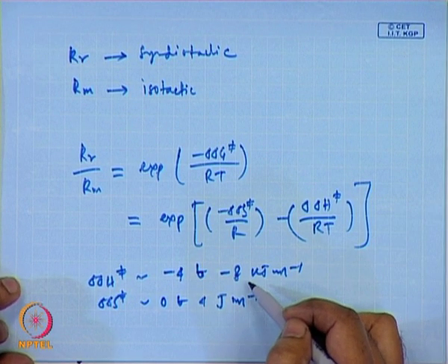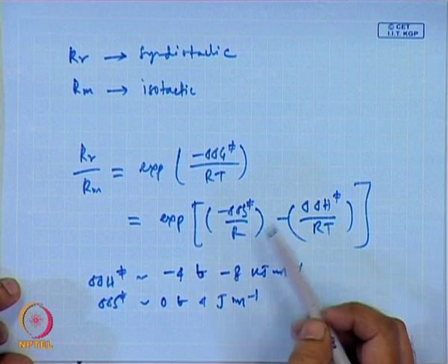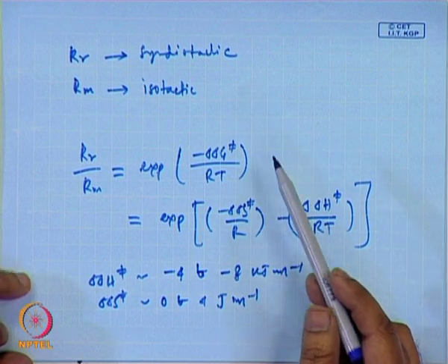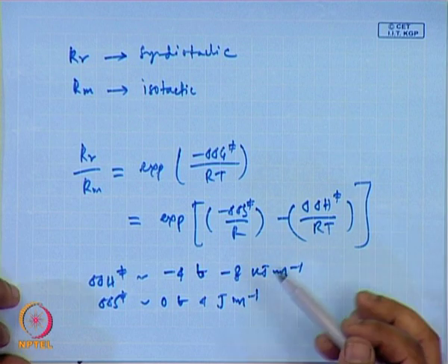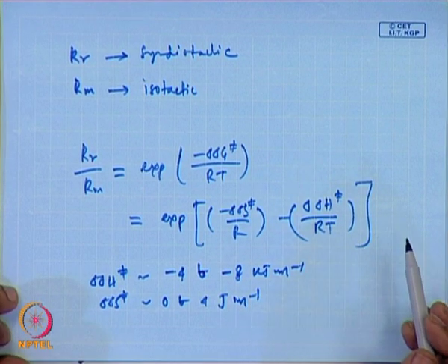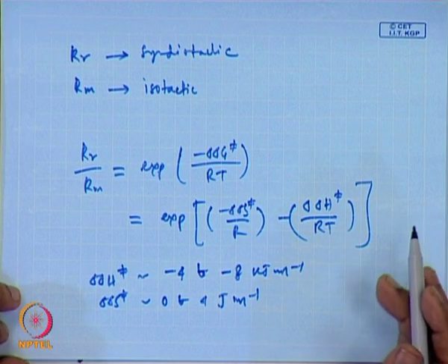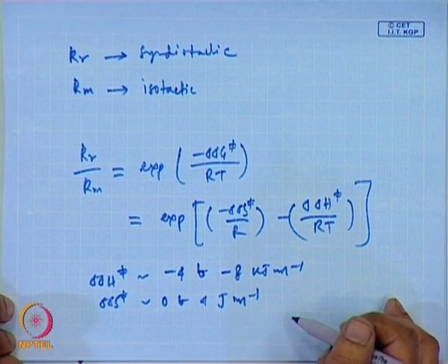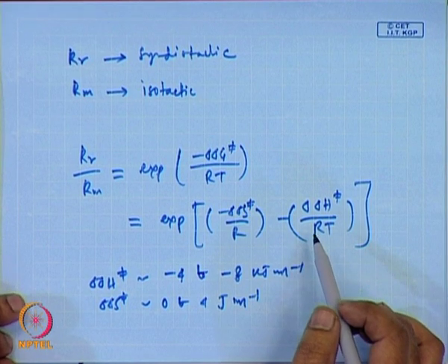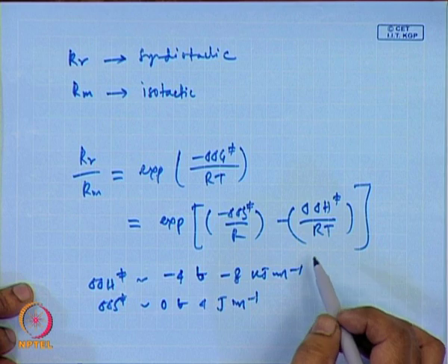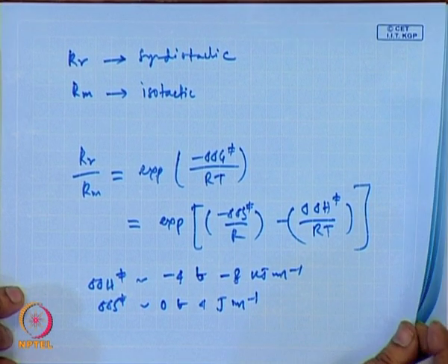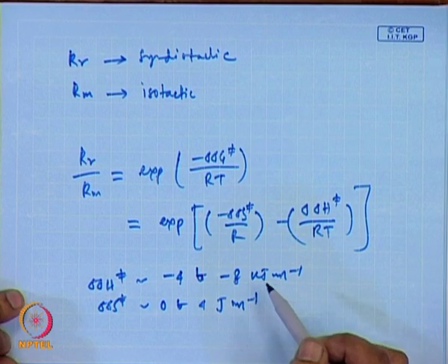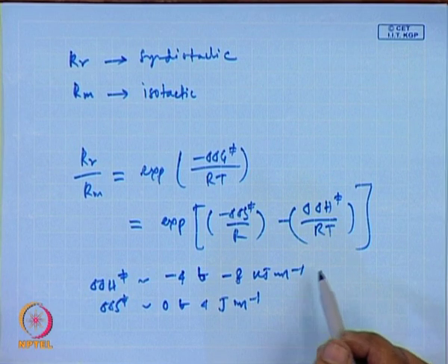activation energies, and if you increase the temperature there will be no preference between these two, and hence there is a tendency for either of the two stereoregular forms to form, which will lead to an atactic polymer. If you reduce the temperature, obviously there will be an increased tendency of syndiotactic polymer formation.